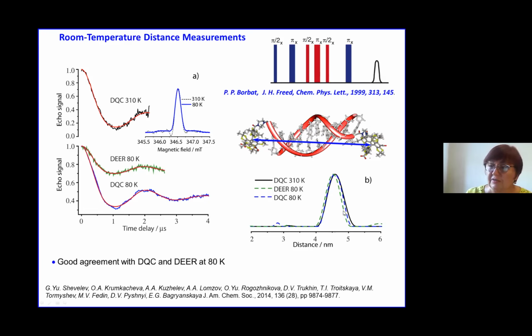That is not always the case. Sometimes it is different, but for oligonucleotide, we got the same result. We also confirmed it by NMR because it is quite a simple system. And that was validation. And I should say that nowadays, a lot of groups try to perform experiments at room temperature. The idea here is to take very large protein, which rotates much more slowly than the Larmor frequency, and then one can try to perform experiments at room temperature. We also tried, but we failed till now because we have no such a large protein and good biological problem for that.